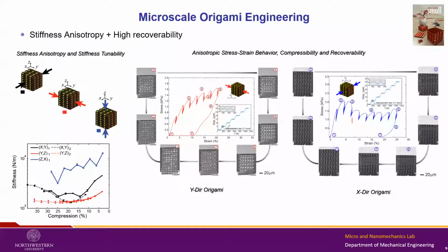We didn't do a simple cycle of compression and unloading. We did stepped compression and recovery phases, as you see here. We compress, and then we cycle back and forth, and that allows us to study the stiffness tunability of these metamaterials as the overall compression of the structure progresses. We were able to see that the stiffness does change with compression depending on the orientations, and as you can see here in the pictures, we were able to retrieve that foldability, which was one of the main challenges that we had, and what distinguishes origami designs from other kinds of materials. You can compress these structures to 30%, and then you can recover up to 96%. So that was pretty encouraging as well.